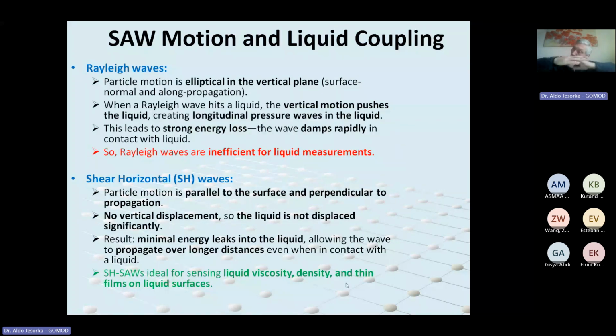You have to take care that you also have, by design, little energy leak into the bulk material. If that is being taken care of, you can get excellent, very sensitive sensing devices for liquid viscosity, for density, for thin films on liquid surfaces. If you, for example, functionalize the surface, you can detect the attachment of antigens to antibodies or similar.